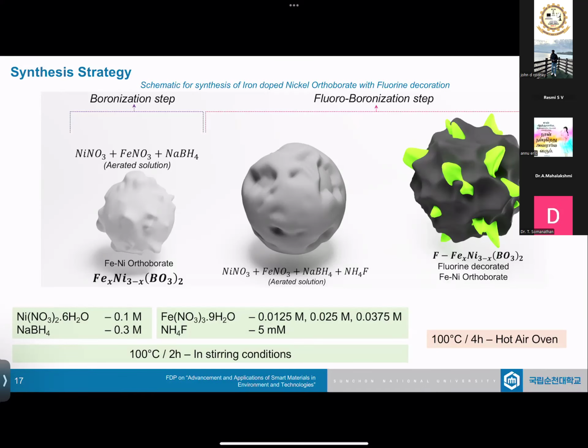Let's say you select a material of one family, like I've selected the orthoborates. The reason is that we know the BO3 minus framework is a very stable framework, even in harsher conditions. As an electrolyzer-based researcher who works on hydrogen production and storage applications, I know water electrolysis is a very harsh process, which puts too much stress on the lattice, the planes, the morphology, the chemical bonds, and the coordinates, even on the bonding nature of the material, where it is well known that the material tends to alter itself while the mechanism is being processed to achieve the best setup to produce hydrogen or oxygen. So in that way, we know that BO3 is a very strong setup, and we wanted to use it.